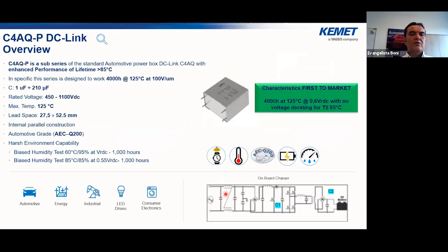Here we have an overview of the new C4AQ-P. In C4AQ-P, the P stands for performance, so it has increased performance versus the standard C4AQ, due to the fact that this series can work up to 4,000 hours at 125 degrees at 100 volts per micron. That means it's 0.6 of rated voltage.